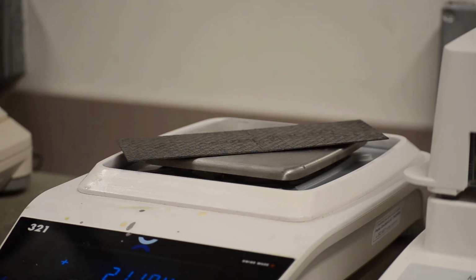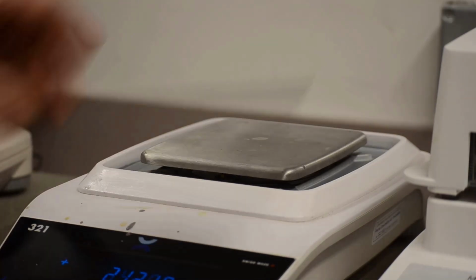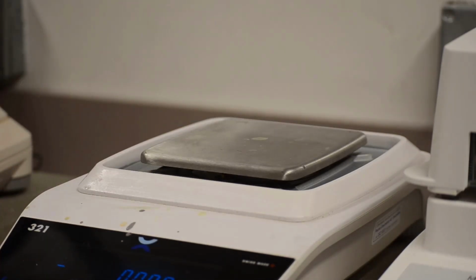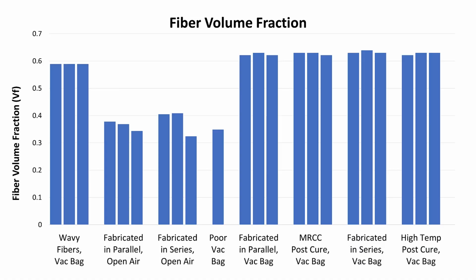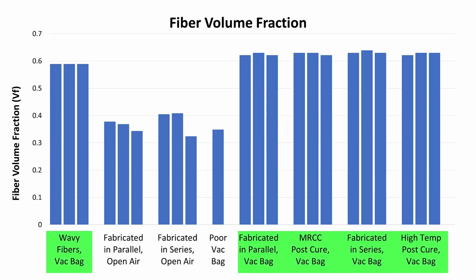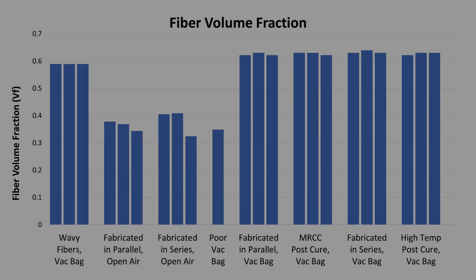A part with a higher ratio of fibers to matrix will generally have superior mechanical properties as long as the fibers are fully saturated with resin. We can see that the vacuum-bagged parts had a consistently higher fiber mass and volume fraction than the open-air cured parts, which typically means higher strength and stiffness per mass.